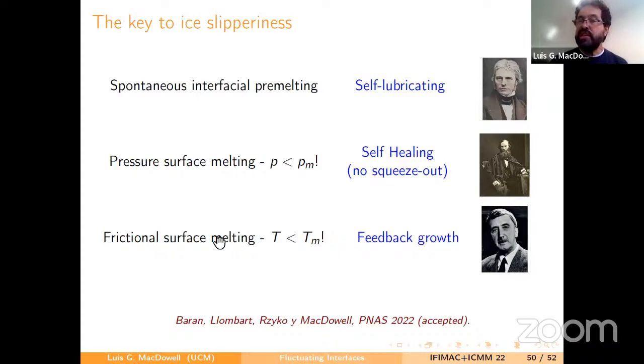And when you get sufficiently high sliding speed, then you also have frictional surface melting. And this gives a mechanism of feedback growth of the film that is also occurring well below the melting temperature. Okay, so these are perhaps some of the keys of ice slipperiness, and we got this accepted just 1 week ago.